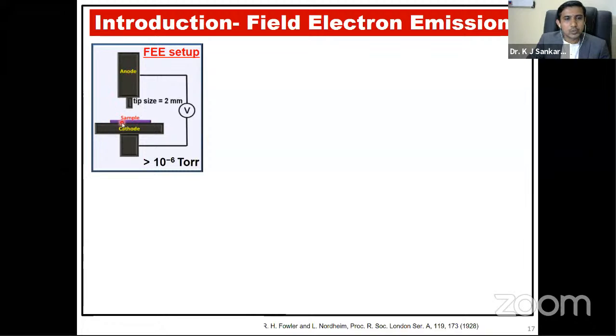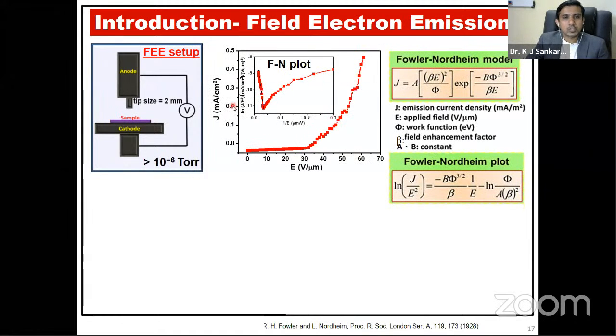The cathode, we use the sample, that is the diamond coated on the silicon, and the anode having a very sharp tip of around 2 mm, made up of a molybdenum material. So this field electron emission setup, the experiments will be carried out in 10⁻⁶ Torr. So these are the results we achieved from the field electron emission measurements.